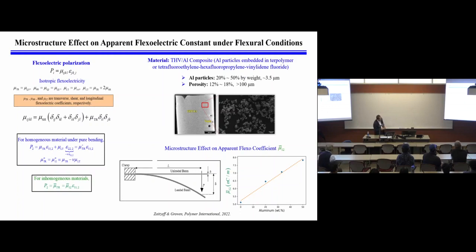But even those two constants, for such a simple case, are still coupled when you use a bending experiment, meaning that both components contribute to give you the apparent electrical output. It's not possible to separate them from the experiment alone. Even if you do a bending experiment, you will have the two strain gradient components. It's not possible to have just one. So we wanted to separate that using simulations, computations.